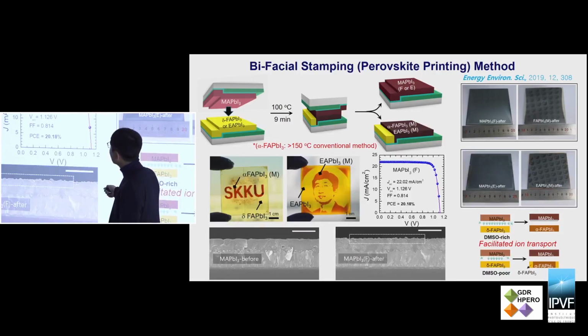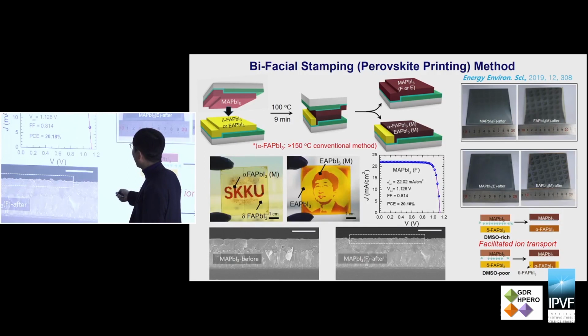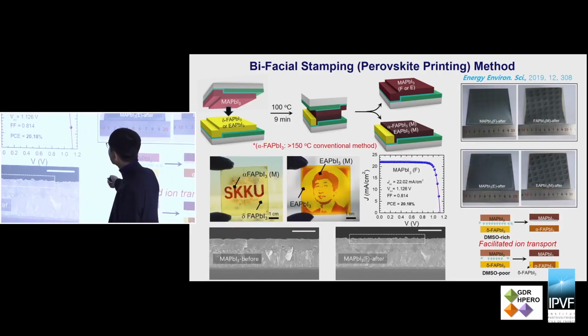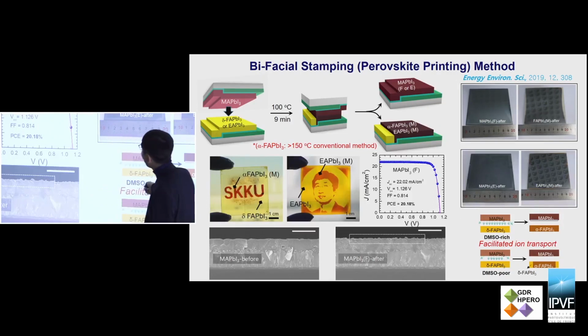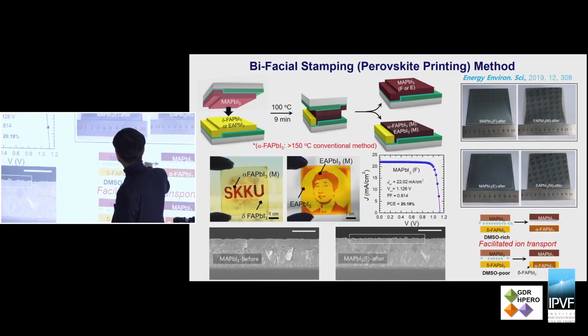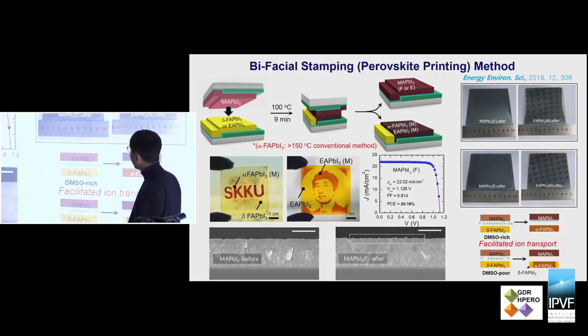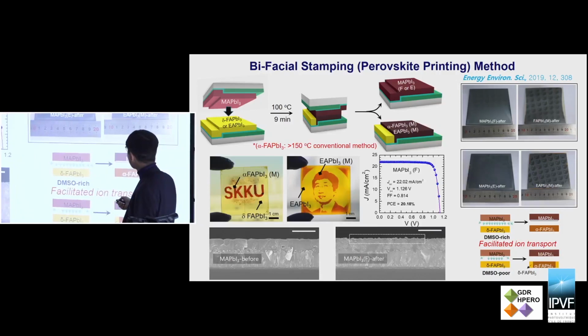Therefore, after this bifacial stamping process, you can get MAPbI3 with a surface-modified structure, and also black alpha phase FAPbI3 at a lower temperature, milder condition. Probably this is due to a small amount of methyl ammonium going into the FAPbI3, so it is stabilized at low temperature. And this method actually gives a higher efficiency, and also a very large area device, the perovskite film. We could not prove the mechanism behind this bifacial stamping method. Probably some facilitated ion transport mechanism may be involved. So we are now studying to prove this facilitated ion transport reaction.